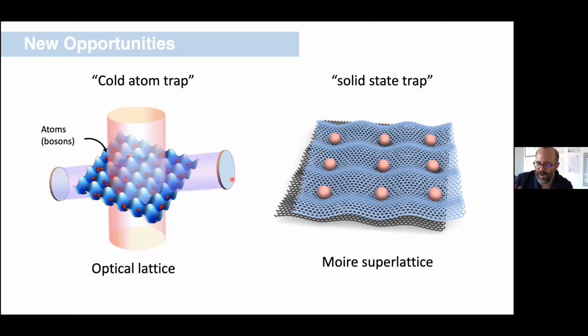So sorry, the answer is a little bit complicated. The actual conversion from strain to cyclotron gap depends on the strain gradient, so it depends on the precise shape of the thing. I don't have a good answer in the moment, but for our bent beams where we know what the average strain is, the average strain is a few percent. We think we can get to about a half a Tesla, maybe as much as a Tesla in these systems. So that's not an enormous amount in this geometry, but that is a measurable amount. We are conceiving of other geometries where we might be able to push that up. We're limited by the breaking strain, which is say 5%.